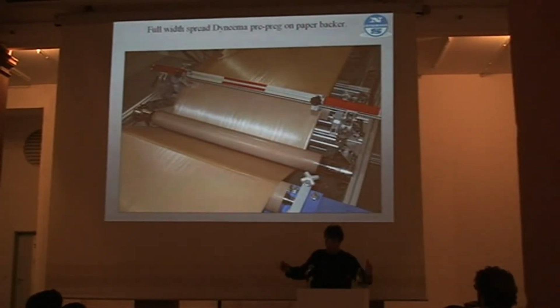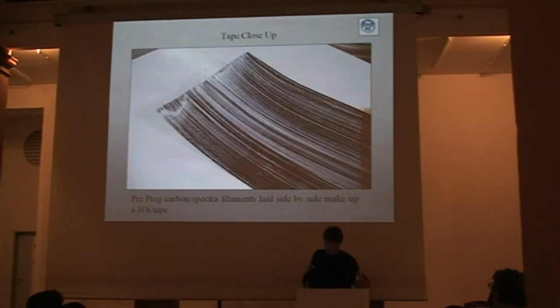So here's a roll of thin Dyneema tape, about 30 grams per square meter. And again, the brown is just the paper backer that the resin and the Dyneema are laid onto, so we can roll it up or pull it off the roll. The material is then slit down to different widths for creating the structure. And this particular one is an example of a pre-impregnated tape that's both Dyneema and carbon fiber. So the white stuff there is the Dyneema, and the black is the carbon fiber.